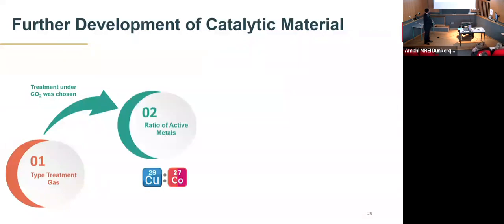The next step of our material development was the introduction of a secondary active metal. In this case, we introduced cobalt as a secondary active metal, and we used different ratios of copper and cobalt in order to see its influence on the catalytic activity. Upon comparison of the catalytic performance, we saw that the cobalt-copper ratio of 2 gave us the best catalytic performance and therefore was chosen for the further studies.